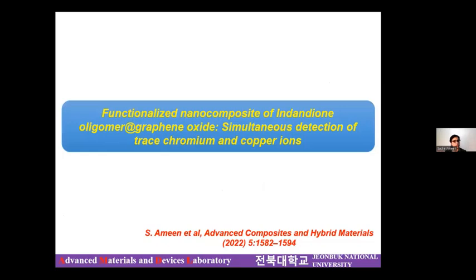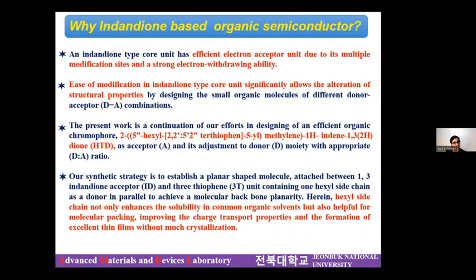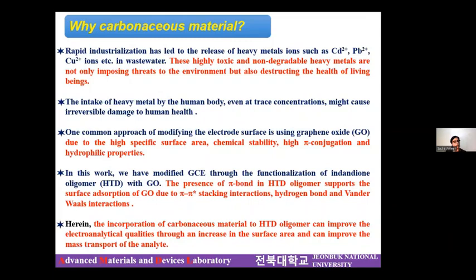Lastly, I will quickly discuss the applications of organic molecules for the detection of heavy metal ions, for example, chromium and copper. Here we have designed a specific molecule, which we have named an indandione-based organic semiconductor. The hexyl side chain enhances the solubility in common solvents, and it is also helpful for molecular packing, for improving the charge transfer properties, and for the formation of excellent thin films without much crystallization. And for using it in the detection of heavy metal ions, we made a composite of this synthesized organic molecule with a carbonaceous material.